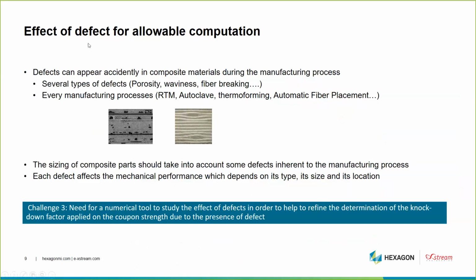A last challenge is the possibility to take into account the effect of defects when we compute the allowables. We know that defects appear in the composite material during the manufacturing process. We have several types of defects, such as porosity, waviness, or fiber breaking, and those types of defects appear no matter the type of manufacturing process that we are using. Porosity can often be associated with the RTM process or autoclave. Thermoforming can lead to waviness or fiber breaking. Automatic fiber placement can lead to the presence of gaps in the coupon.